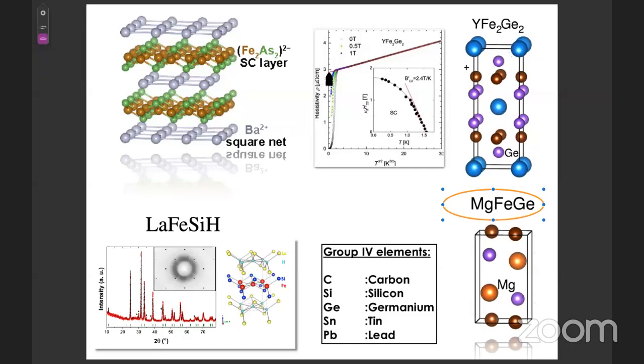So it shows some superconductivity around 2 Kelvin, but this is an intensively debated material. Its electronic structure is similar to that of calcium iron arsenic in the collapsed tetragonal phase, but with significant electron doping. This led to the speculation about a connection between superconductivity in yttrium iron germanium and the collapsed phase of the extremely hole-doped potassium iron arsenic. Furthermore, Wang et al. recently found yttrium iron germanium to be close to a magnetic instability, and X-ray absorption and photoemission experiments show strong spin fluctuation and moderate correlation effect in this material.